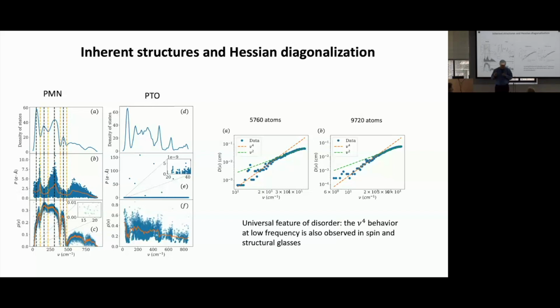We have to minimize the number of quantum mechanical calculations, because even though DFT is not as expensive as quantum Monte Carlo, it is still quite expensive when we have to sample tens of thousands of configurations. So we do the sampling with a deep potential model that is refined iteratively. When the spread in the prediction for the forces exceeds a certain threshold, it means we need to acquire new quantum mechanical data.